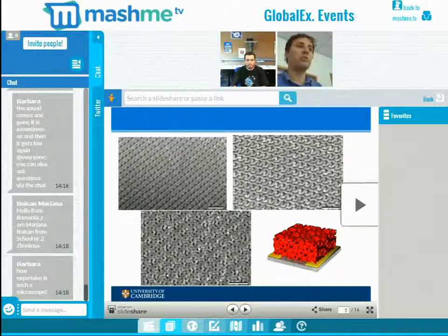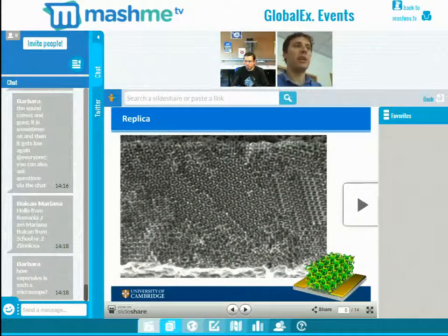And then when we use these porous polymer films as scaffold templates for metals, that's how the metals look. Again, you see this wiggly structure, which is a three-dimensional structure, and the diameter of one of these structures is only 10 nanometers. So these are extremely small samples.